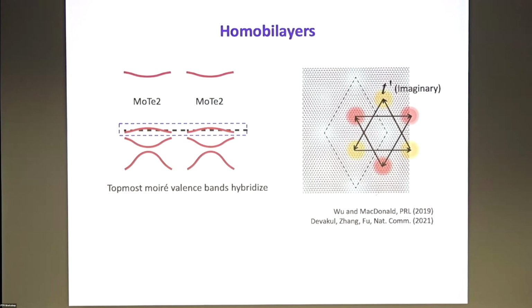And the reason is sort of the following, that each of these bands has a Wannier orbital that forms a triangular lattice, but together they form a honeycomb lattice. And because they are K electrons, the hopping is imaginary. So it's already a bit looking like the Haldane model. And together with this skyrmion lattice feature that Allen talked about two days ago, due to the interlayer hopping term here, the interlayer hopping is also a complex number. And that will actually generate exactly a Haldane model in each valley in certain twist angle.